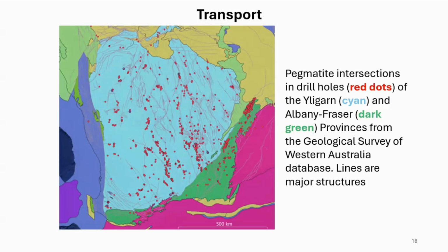So shear zones seem to be conduits for pegmatites. We've done statistics on it, and there is a statistical correlation between the occurrence of gold deposits and the occurrence of lithium pegmatites, but that doesn't mean they're cogenetic. The gold deposits don't have to be the same age, they can have completely different sources, they're just using the same conduits. Gold deposits use shear zones as conduits, pegmatites use them as conduits. So it's not surprising that we get gold deposits and pegmatites associated with major shear zones.